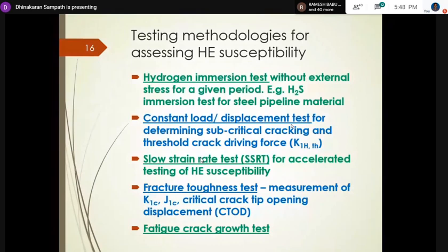So how do we evaluate the susceptibility of a material? Depending on the service environment and the steel type, they subject it to different tests. For example, there are some low alloy steels used as pipeline material that carry hydrogen sulfide. For this material, they just take a piece of material and immerse it in the H2S solution without applying any external stress, and then see if there is any crack.